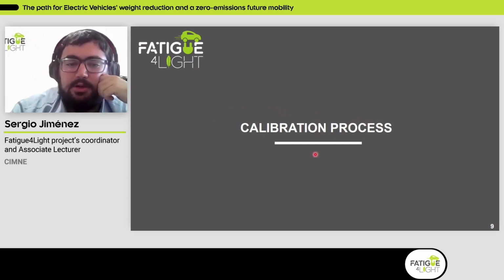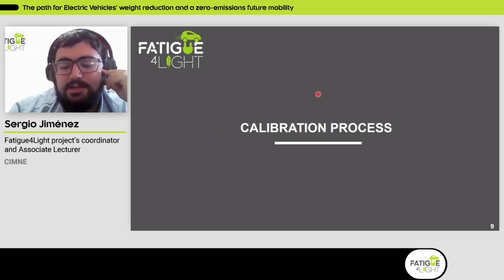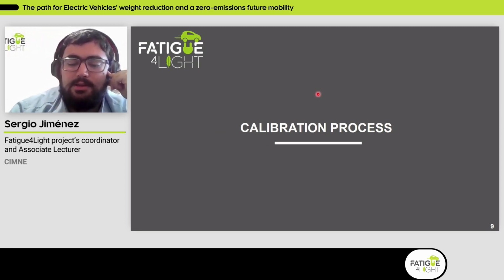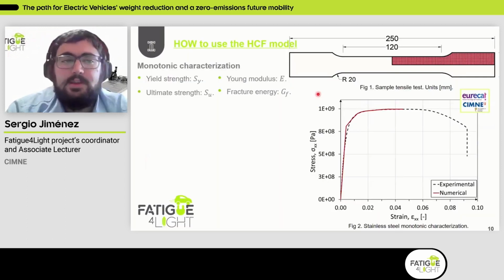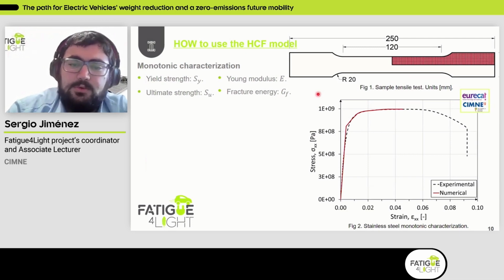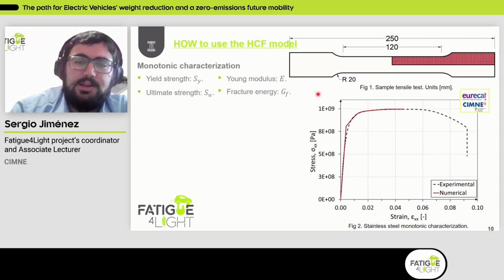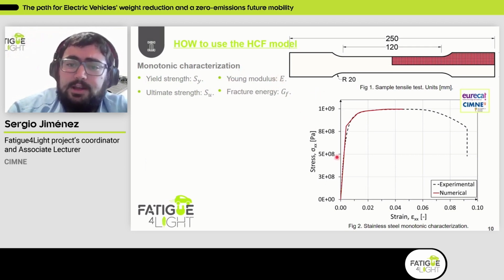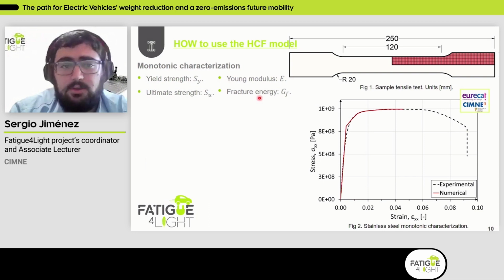So I will be talking now about this calibration process that we followed in the Fatigue4Light project, and that needs to be done while using the numerical model that we are proposing. So basically what we do while calibrating the model is, first of all, focus on the monotonic characterization. And by doing that, basically what we are achieving is characterizing the yield strength of the material, the ultimate strength, the Young modulus, and the fracture energy of our material.